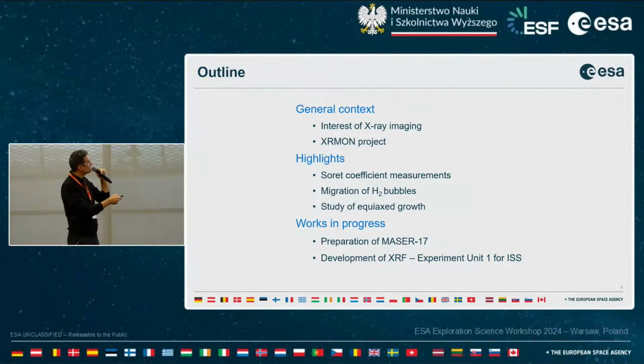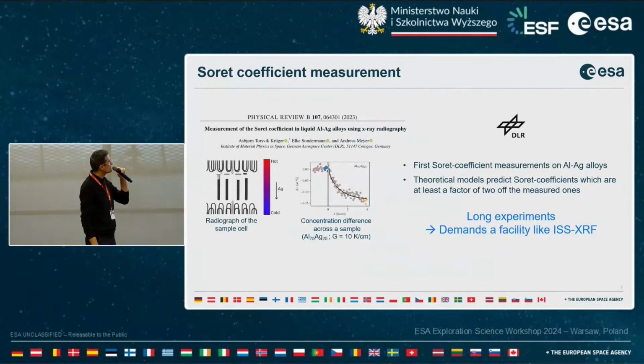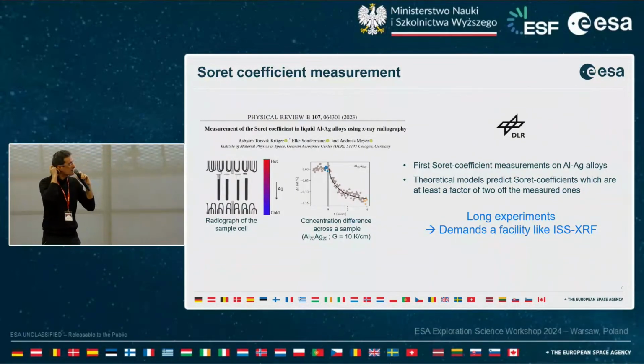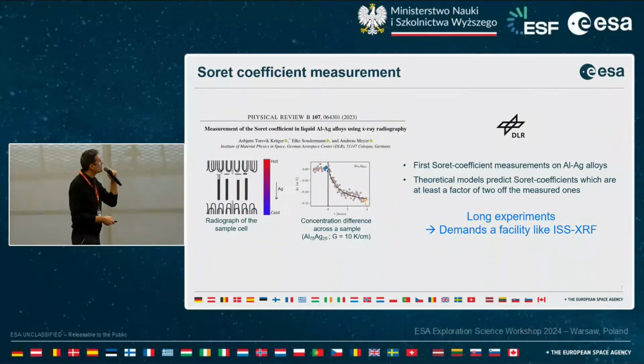The first one will be related to diffusion processes. It's about the Soret coefficient measurement. So the Soret coefficient is a parameter that characterizes so-called thermodiffusion effects that you have when you apply a temperature gradient to an alloy, and through thermodiffusion you will have a migration of the different elements of the alloy. And the Soret effect is very well known in fluid dynamics.